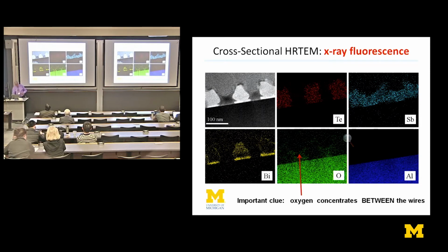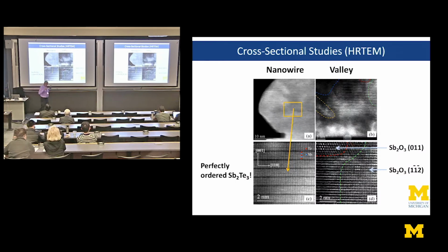And then it was time to look in even more detail and really get down to details where we can see individual atomic layers. So this is a nanowire region. And I don't know if you can see this where you are, but these layers here are the quintuple layers separated by van der Waals gaps, and there's a blow-up. There's a zoom in here where the darker regions are the van der Waals gap, and then there's 5 layers, and then another van der Waals gap, and so on.